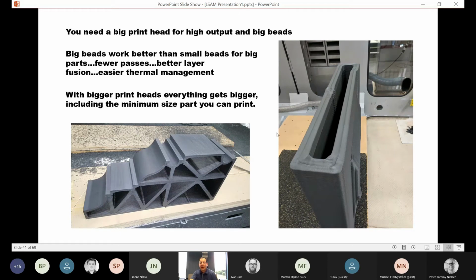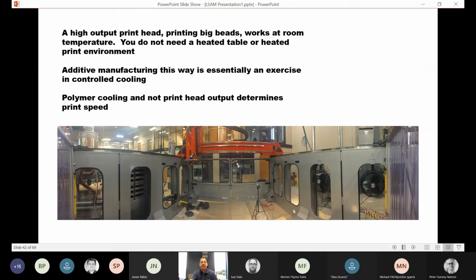You need a big print head for high output and big beads. Big beads work better than small beads: fewer passes, better layer fusion, easier thermal management. With bigger print heads, everything gets bigger, including the minimum size part you can print. A high output print head, printing big beads, works at room temperature. You do not need a heated table or a heated print environment. Additive manufacturing this way is essentially an exercise in controlled cooling. Polymer cooling and not print head output determines the print speed.